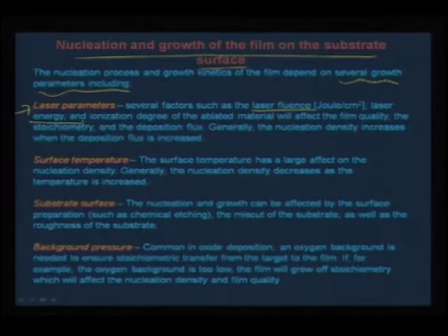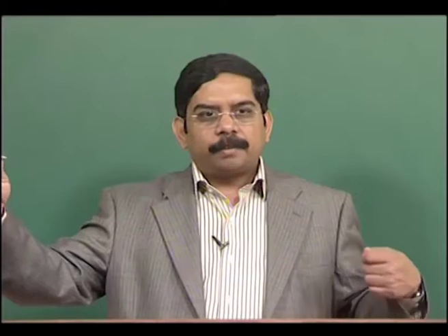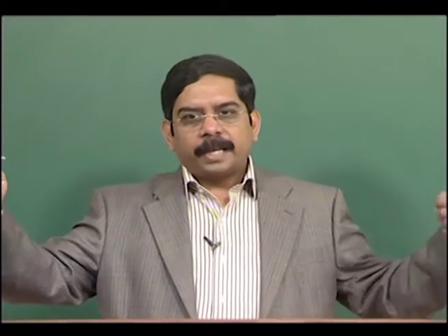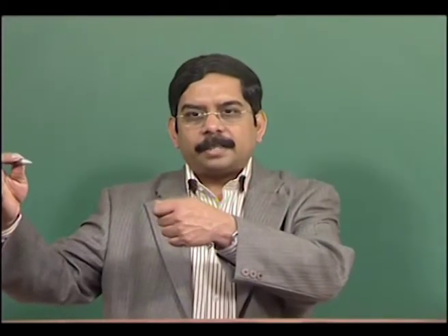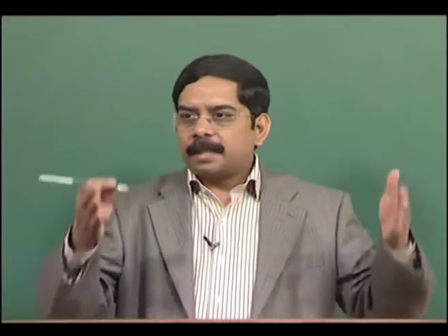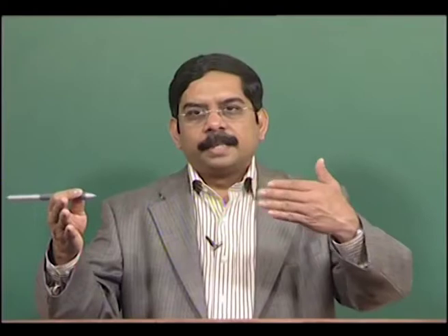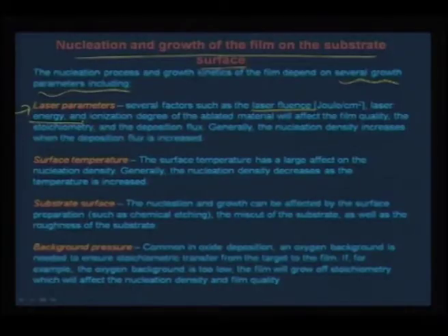In fact, there is a calibrating instrument which will tell whether you are getting the required laser energy before every deposition, because continuously, since the coating is done, the optics can also take this ablation and it can filter the laser light from reaching the source to the fullest extent. Therefore it has to be calibrated.